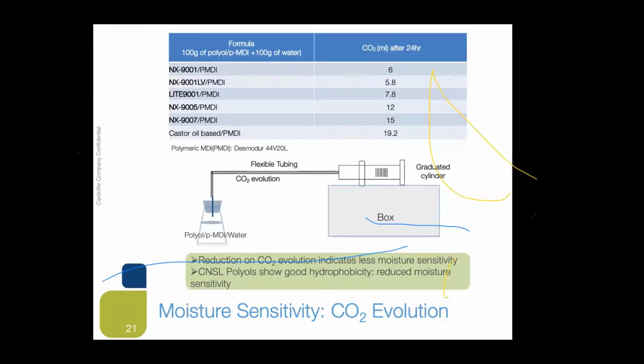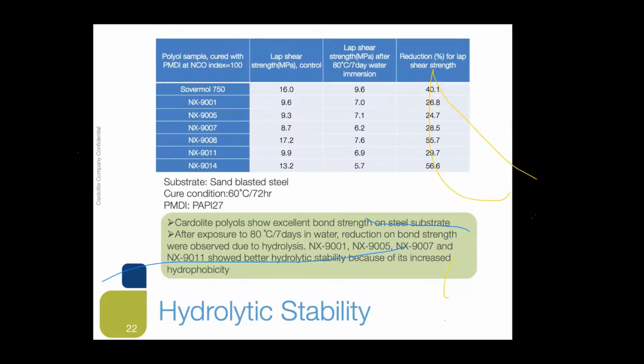And you have a reduced moisture sensitivity. Normally with this kind of technology, CNSL based polyol has less moisture sensitivity. And also we checked the hydrolytic stability. We checked some of the data, and these polyols have better adhesion even on SS surface as well. Even this product has better adhesion on concrete.